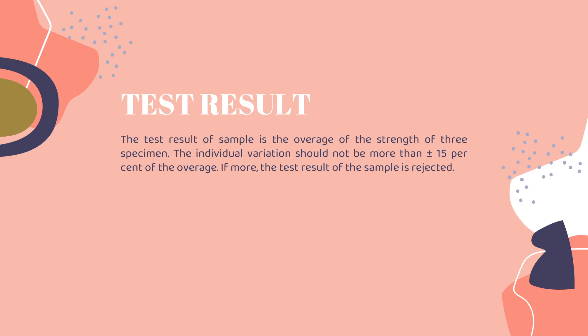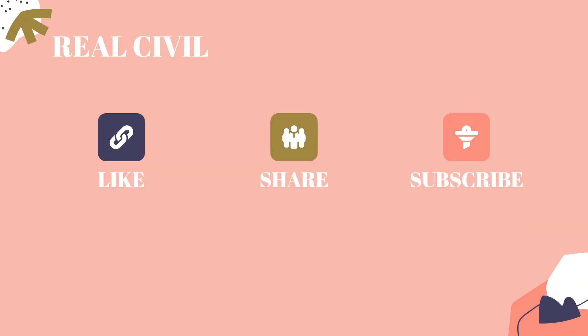The next point is test results. I will cover this in detail in our next video, but here is an overview. Suppose we have cast and tested 3 cubes — if the variation between the cube strengths is more than 15% of the average, then that sample is rejected. What we need to do in that case and what our next step would be — all those things we will cover in our next video.